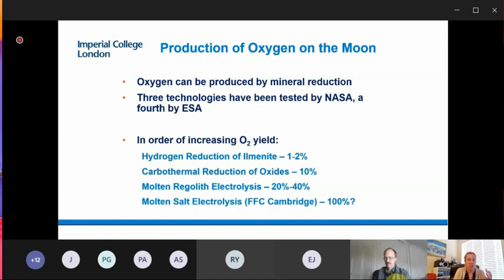a higher temperature. If we go into the electrolysis processes, so molten regolith electrolysis, molten salt electrolysis, then the yields of oxygen are higher, so we produce more oxygen per mass of regolith, of lunar soil that we put into the reactor. But again, the temperatures are higher, so now our energy costs are higher. And we can start to see the trade-off between the production of oxygen and the energy costs. And this is one of the big challenges.